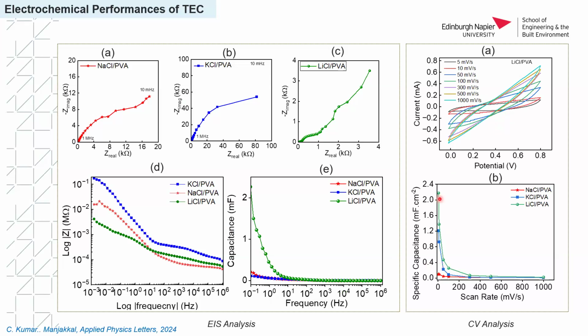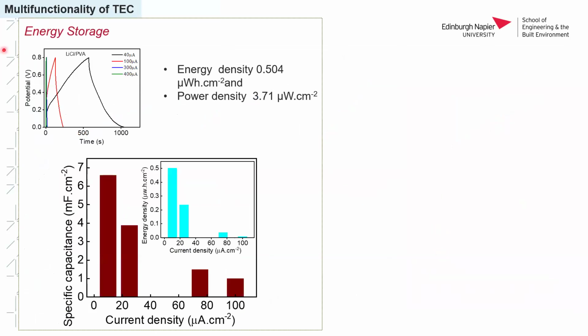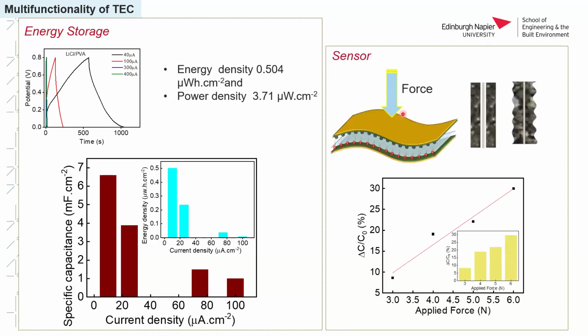Depending on the scan rate, you can see that LiCl shows much better capacitance for this device. Here you can see this LiCl-based TEC working as an energy storage device. You can see the charging and discharging, and the energy density we got is almost 0.5 microwatt hour per centimeter square, which is useful for operating nanowatt electronics applications. But when we apply an external force on top of this, we found that the capacitance changes with the applied force, and when plotting this graph we observed a sloped response compared with the force. Of course, only a limited force can be applied, and we are now trying a high force application.